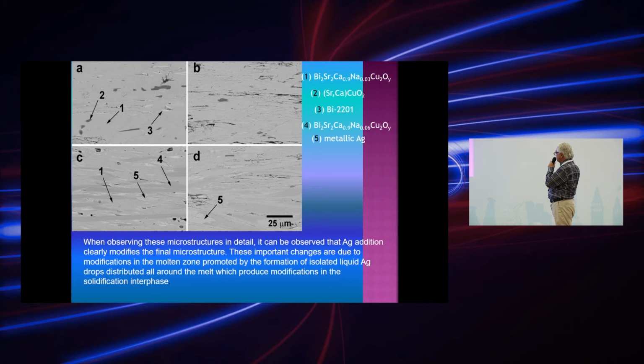By increasing silver addition, we can see here four and five, extra secondary phases. Five corresponds to the metallic silver part. Four is a slightly darker gray, another superconductor phase, indicated as 2 bismuth 2 strontium 0.9 calcium, a little increase in sodium amount, and the others the same. Also, this important change appearing at the higher amount of silver arises from the molten zone promoted by the formation of isolated liquid silver particles all around the melt part, producing this modification in the solidified interface.